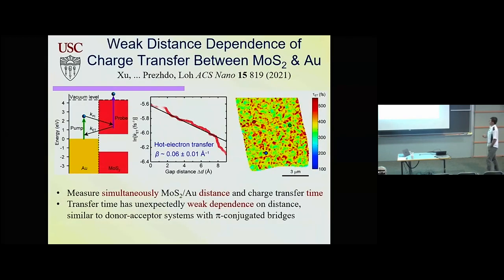So this is a collaboration with a group in Singapore. What they do in this case, they put gold and MoS2 together, and they can simultaneously measure the rate of charge transfer: from photoexciting gold, an electron goes to MoS2. And they could do spatial resolution, and when they do spatial resolution, they can also determine the distance between gold and MoS2. Because the gold surface is rough and MoS2 is flat, you can have variation in the distance. And then they measure rate as a function of distance, and they see this dependence that is very weak.